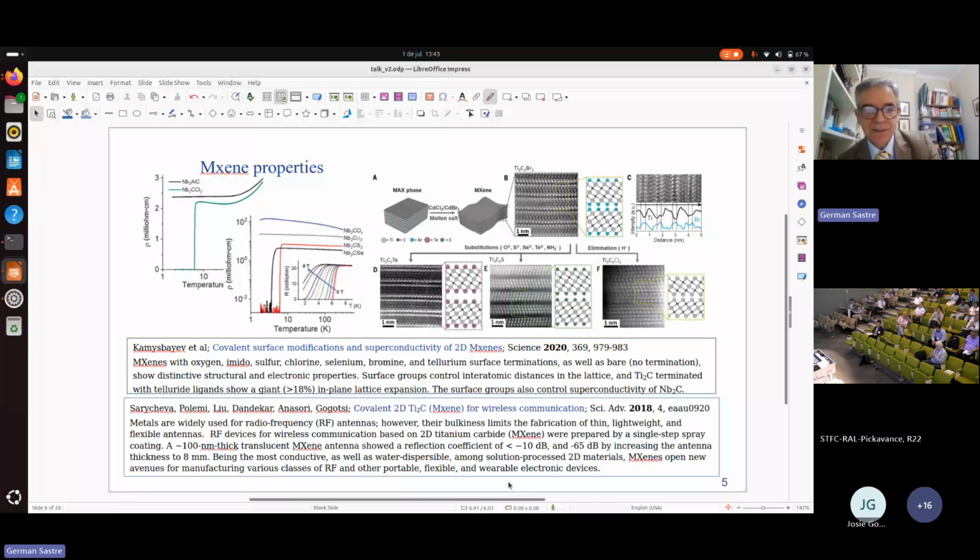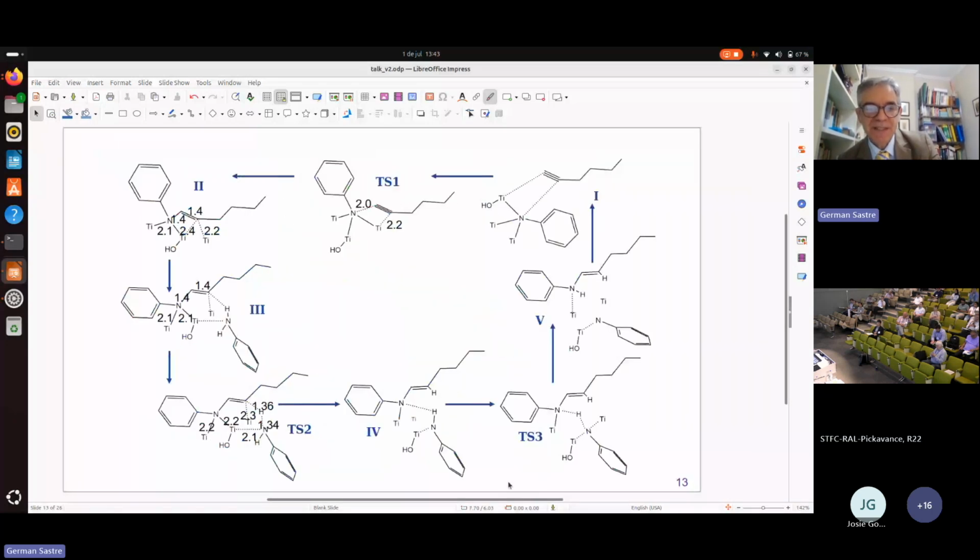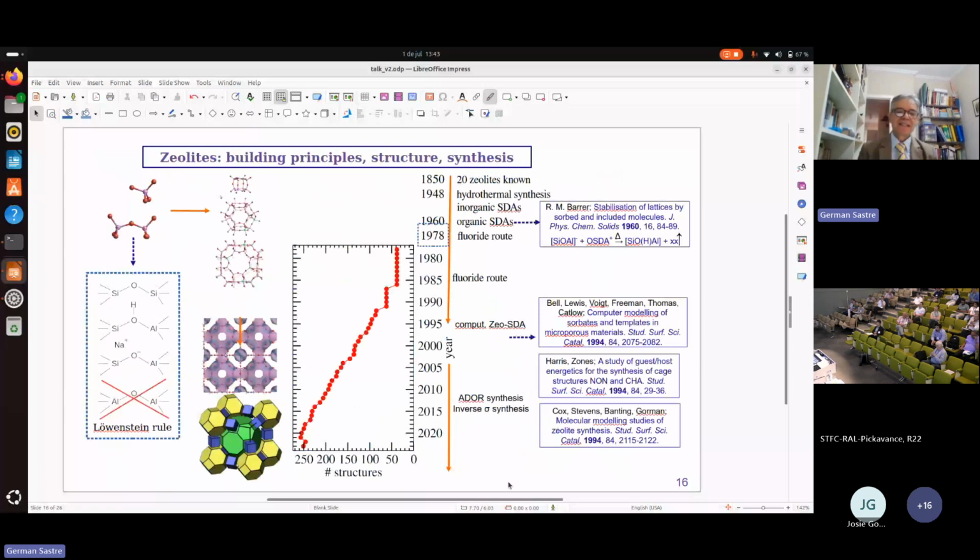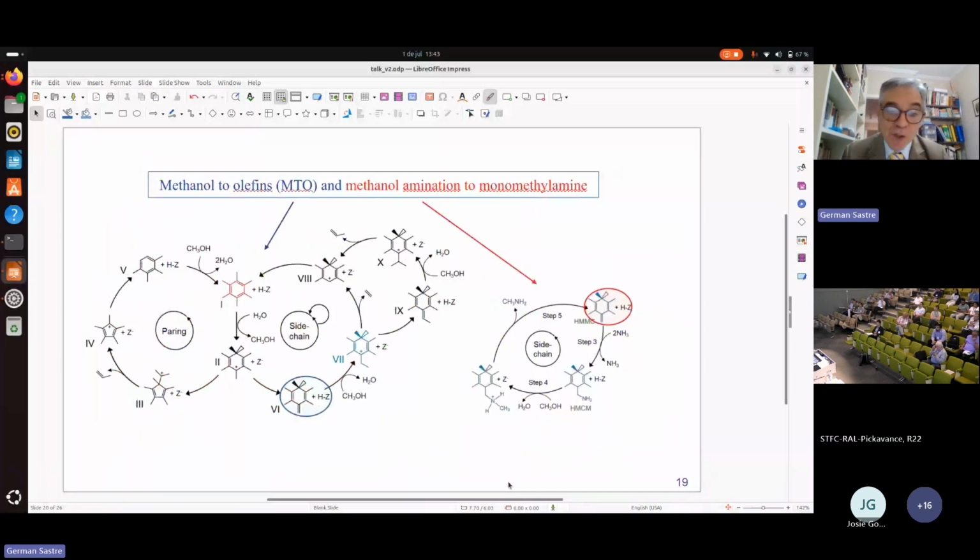I didn't find any, but let me show you if now we can see better from this. No other molecule that I found in the hydrocarbon pool mechanism contains this bond. You've chosen a double bond with a CH2 terminal double bond. Yeah, terminal double bond. This is, let's say, the best candidate, since other molecules containing double bonds are not accessible, since they normally have methyl groups attached. And so that is the only molecule we found that could do the job.